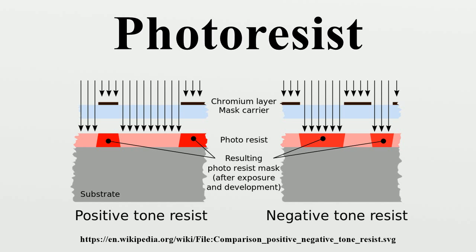The dissociation energy for a C–C bond is 3.6 eV. Secondary electrons generated by primary ionizing radiation have energies sufficient to dissociate this bond, causing scission. In addition, low-energy electrons have a longer photoresist interaction time due to their lower speed. Essentially, the electron has to be at rest with respect to the molecule in order to react most strongly via dissociative electron attachment, where the electron comes to rest at the molecule, depositing all its kinetic energy. The resulting scission breaks the original polymer into segments of lower molecular weight, which are more readily dissolved in a solvent, or releases chemical species which catalyze further scission reactions. It is common to select photoresists for electron beam exposure.